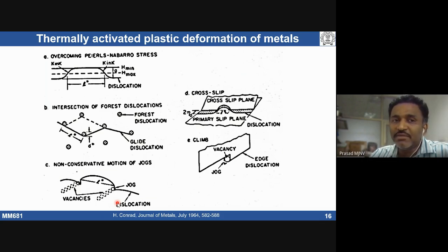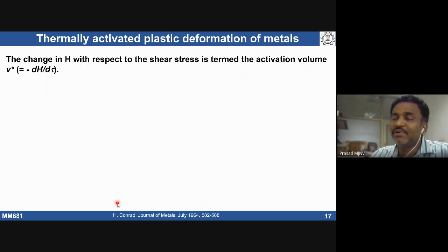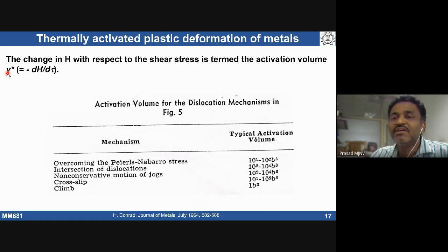So this is another important point. I just introduced a concept, activation energy, which we already discussed. Another important one is called activation volume. The change in activation energy with respect to the shear stress is called the activation volume. With applying stress, the enthalpy or activation energy is going to decrease. This minus dH by d tau is called the activation volume. Each of these thermal barriers will have a particular activation volume. So this table gives some indication.